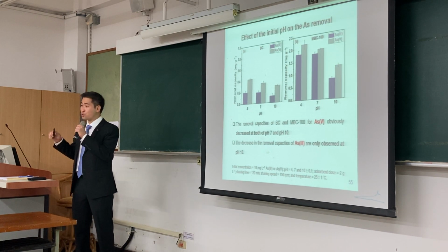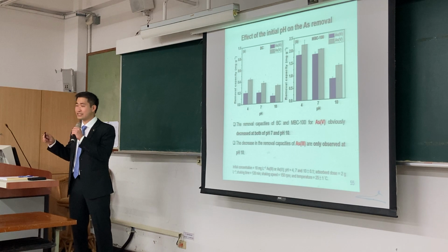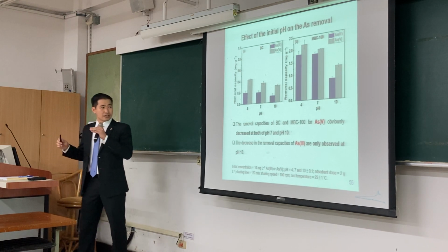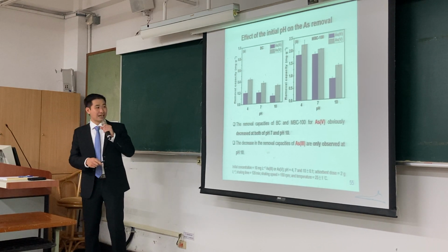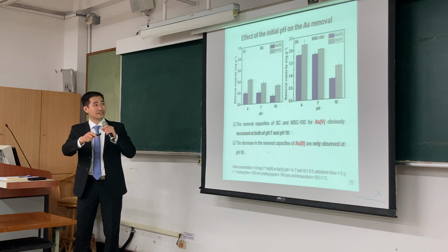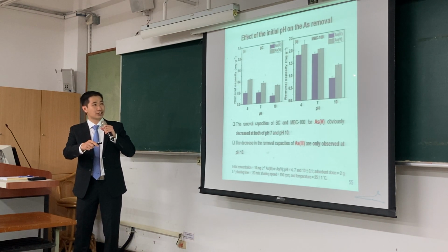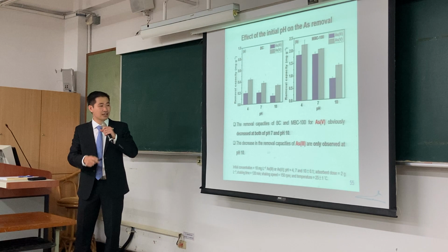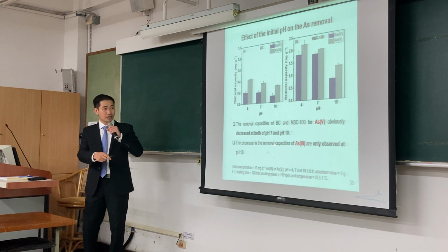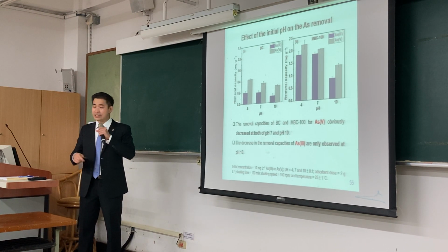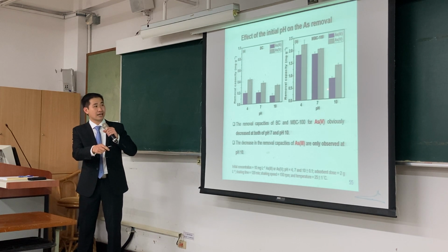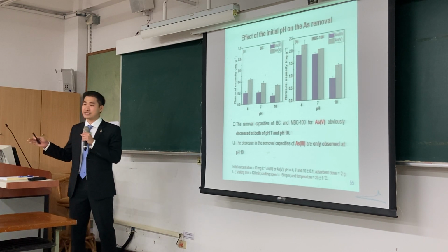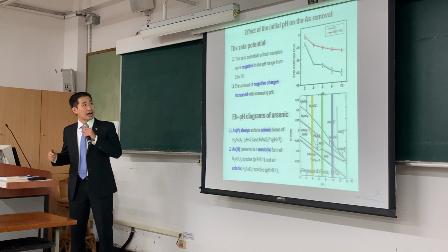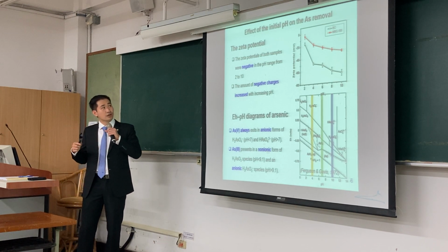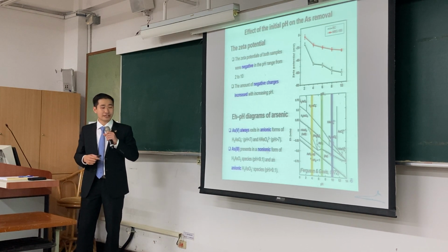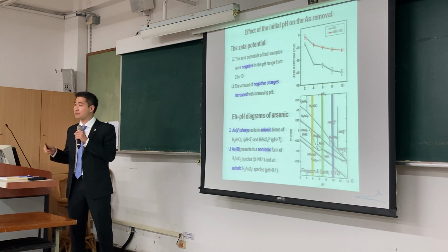Moreover, the effect of initial pH on arsenic removal is presented. The removal capacity of BC and MBC-100 for arsenic 5 obviously decreases at pH 7 and pH 10. However, the decrease of arsenic 3 removal is only observed at pH 10. To explain this phenomenon, I conducted zeta potential measurements and used the Eh-pH diagram of arsenic.